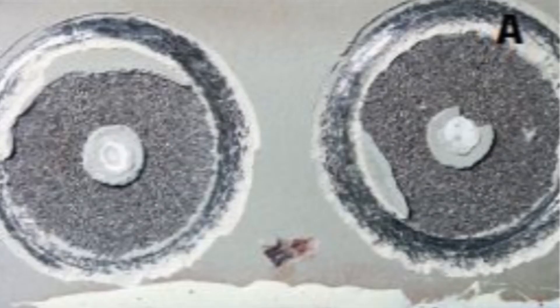Now we look at what the impregnated slag does to adhesion. This is a picture of the slag-blasted surface put to the adhesion test — and it failed. You can see that the dollies popped off of the slag-blasted surface in this test. We now test the GMA Garnet surface. There is strong adhesion with the GMA Garnet, where the glue holding the dolly failed long before the coating would ever come off the surface.